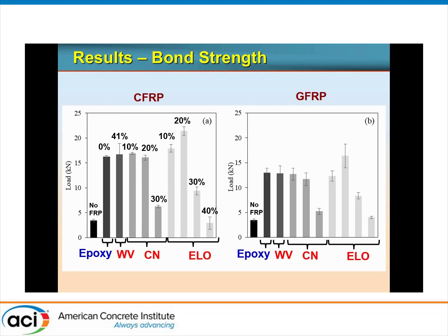So a clear decline from 20 to 30% bio in the CN product. For the ELO, we had 10, 20, 30, and 40, and what appears to be a higher strength here than even the epoxy, but I will caution you about this one. What happens is any specimens that fail by shear in the concrete should be eliminated. So you did not get a bond strength, right? So our average dropped. So there is a bias here because there are fewer specimens.